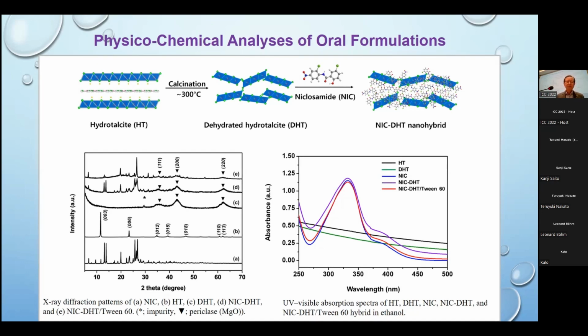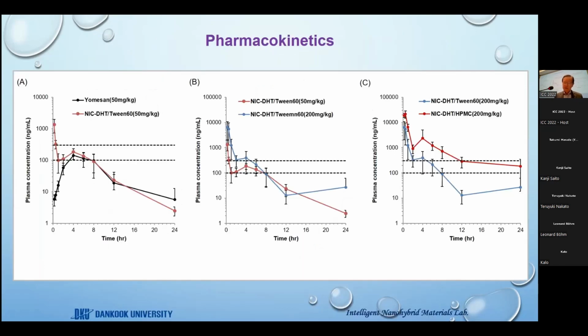Here you can see the pharmacokinetic data, how the plasma concentration of niclosamide is retained with respect to time. On the left-hand side, niclosamide plasma concentration at 15 minutes of NIC DHT twin nanohybrid was around 1,350 nanogram per ml, which is higher than the highest niclosamide plasma concentration after oral administration of the control drug, Yomesan.